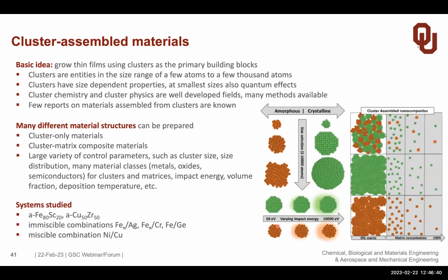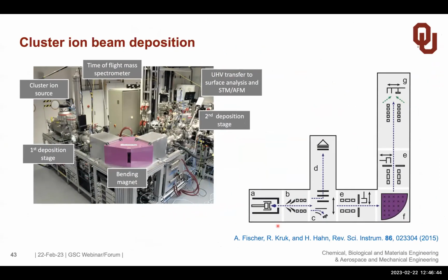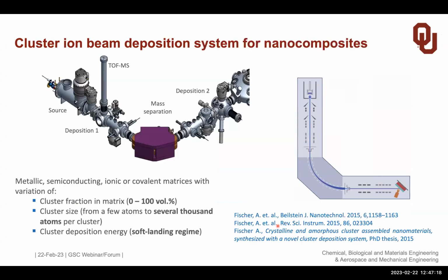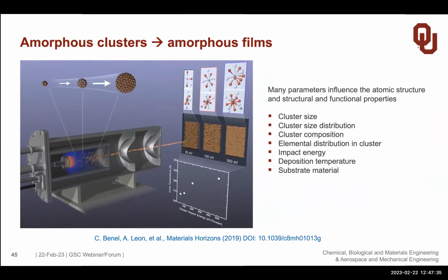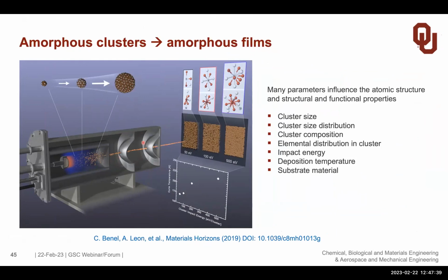And I jump over this, this describes more of these clusters. I show you just our machine, which we are using now. So instead of compaction of particles, we are now using the energetic impact of cluster ions. So very small, a few hundred atoms, large particles, we call clusters, and they are ionized, they have one charge, and then we can accelerate them onto a substrate. And we can change the impact energy when we build a film out of amorphous cluster ions. And this is just a machine. It's a very sophisticated machine which can create clusters in the source. It can form a beam. It can even size select and then deposit the particles here on the substrate. So if you do that, this is a result, and that has been published already about 3 years ago.